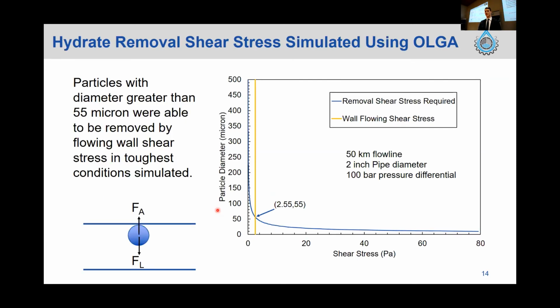And then the last part of this research was just to potentially take it down a different route from the anti-agglomerants and see in Olga to extract some of the shear stresses from a simulation and see how those shear stresses might be able to contribute to overcoming the adhesion force of some of those wall-grown particles. So a nominal case was used in Olga of a 50-kilometer flow line with a 2-inch pipe diameter and a 100-bar pressure differential. And that was basically just a water dominant system.